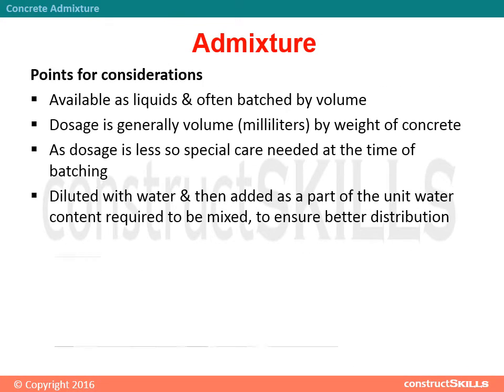Points for consideration: Admixtures are available as liquids and often batched by volume. Dosage is generally measured in milliliters by weight of concrete. As dosage is small, special care is needed at the time of batching. They are diluted with water and then added as part of the unit water content to ensure better distribution.